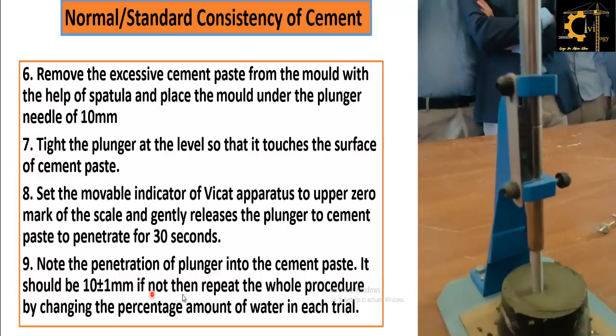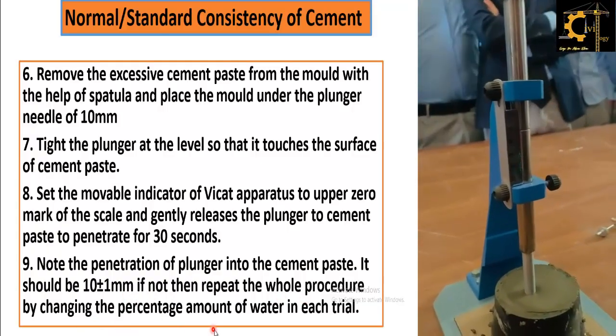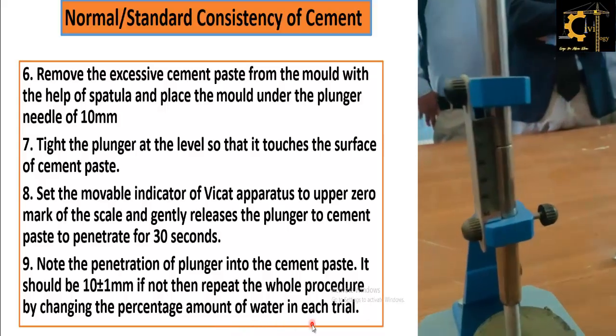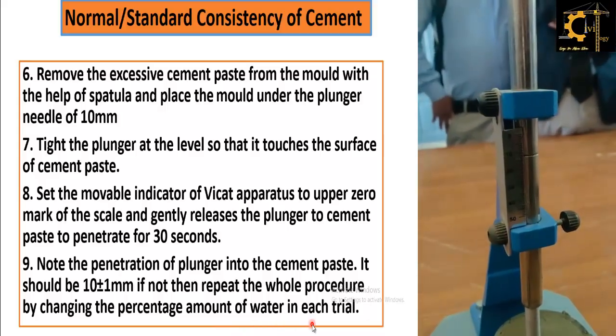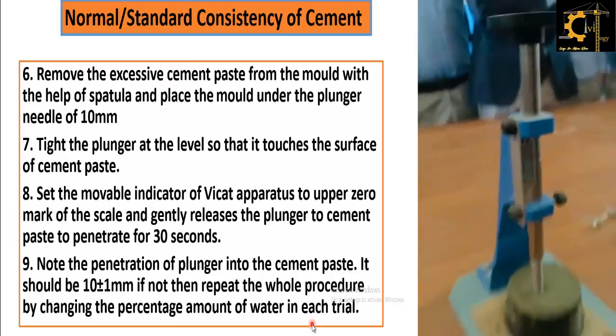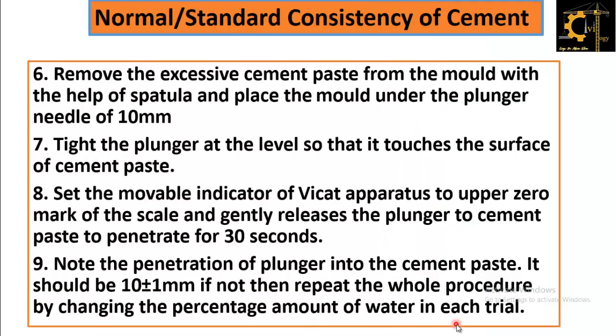If not, then repeat the whole procedure by changing the percentage of the amount of water in each trial. If the penetration is more or less, then you will have to vary the percentage. As I mentioned before, the value ranges from 26% to 33%, so you can choose any value within it according to your result. If penetration is low, you can increase the amount of water. If penetration is high or greater, you can decrease the amount of water by 1 or 2%.